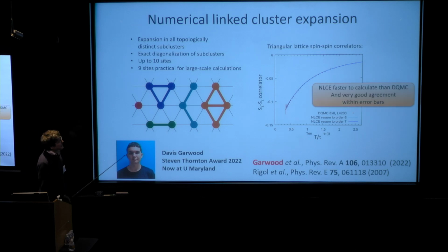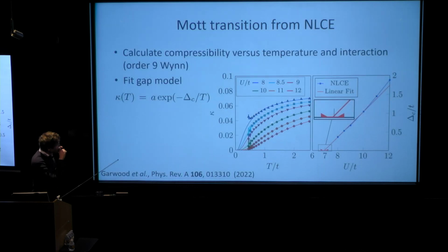So in conclusion, the story is that at very strong interactions, so at relatively large U over T, this NLCE technique works very well, and it's computationally faster than the QMC. And so a little more advanced slide is here. We try to push that a little bit and follow some ideas other people came up with to look at the Mott transition.